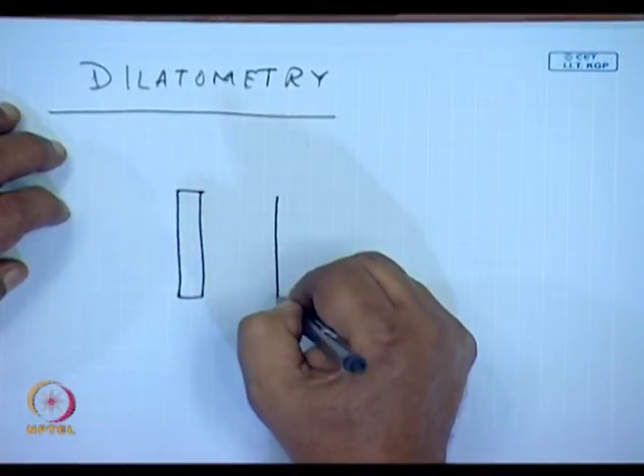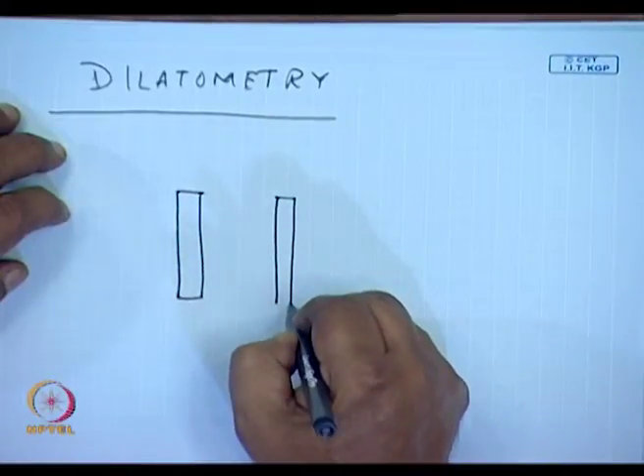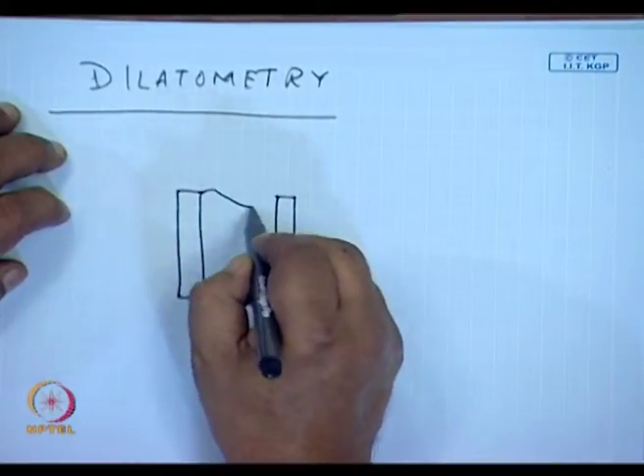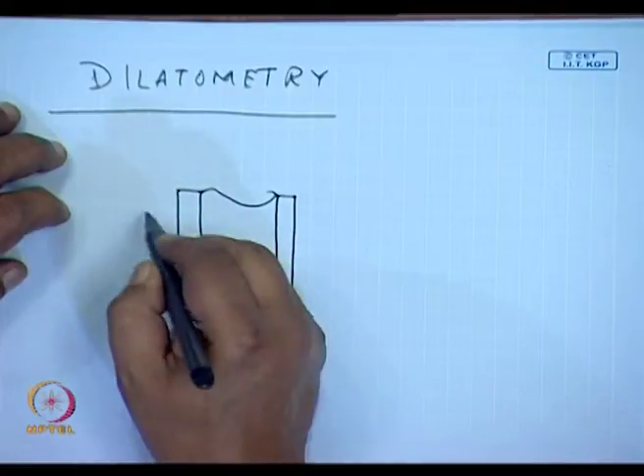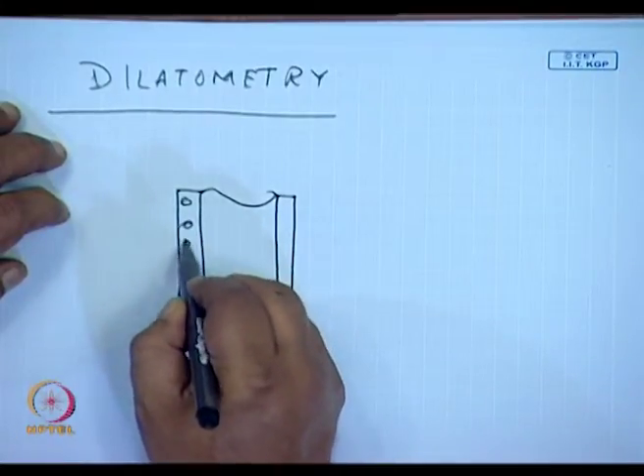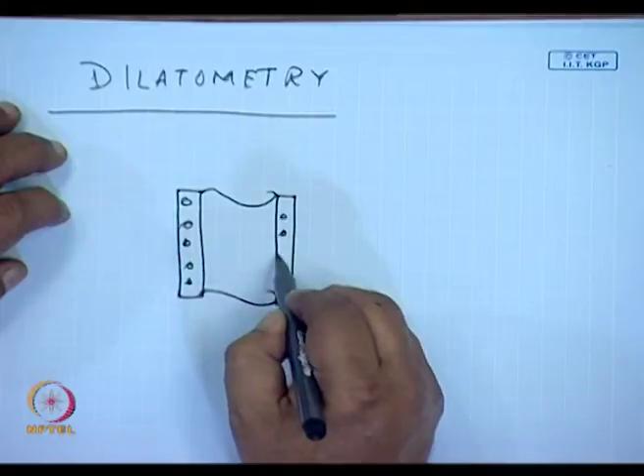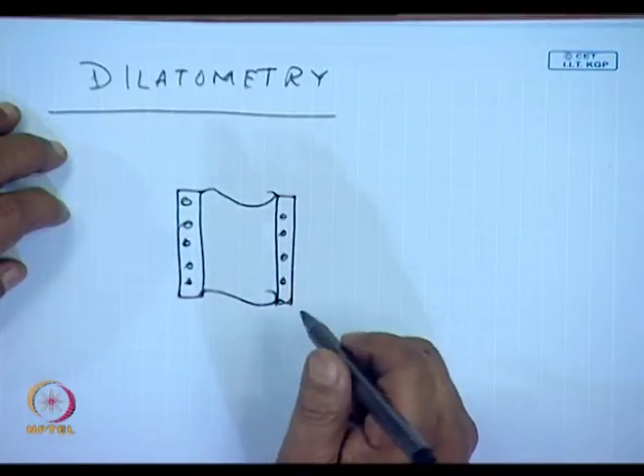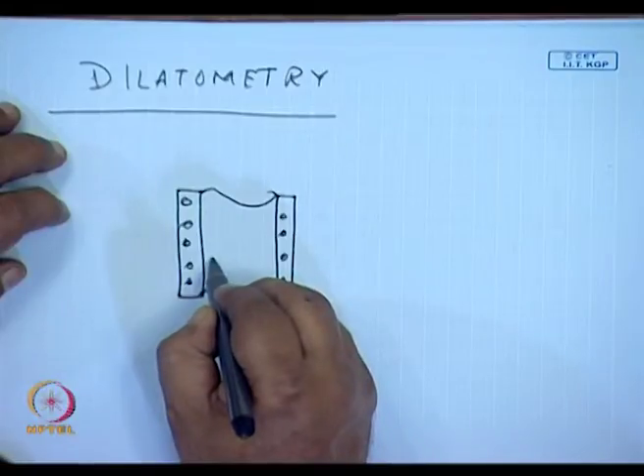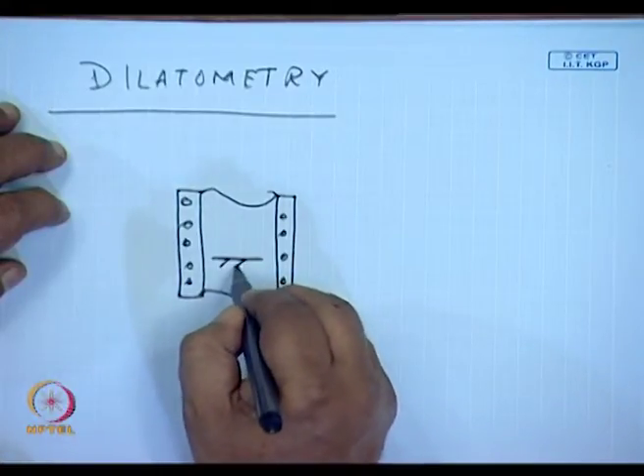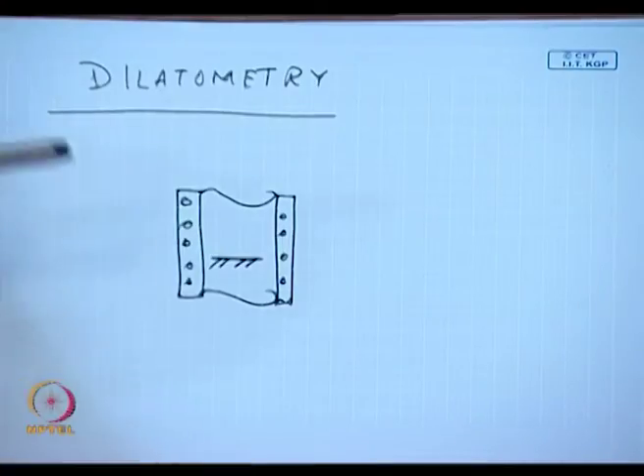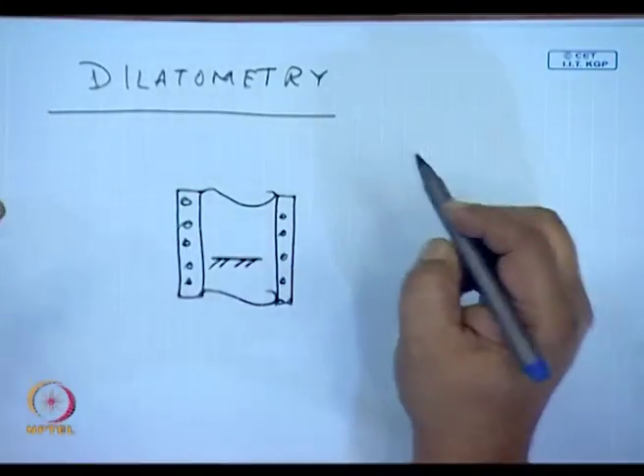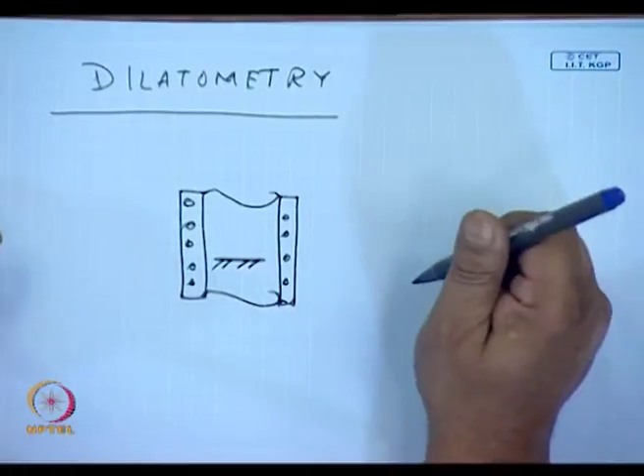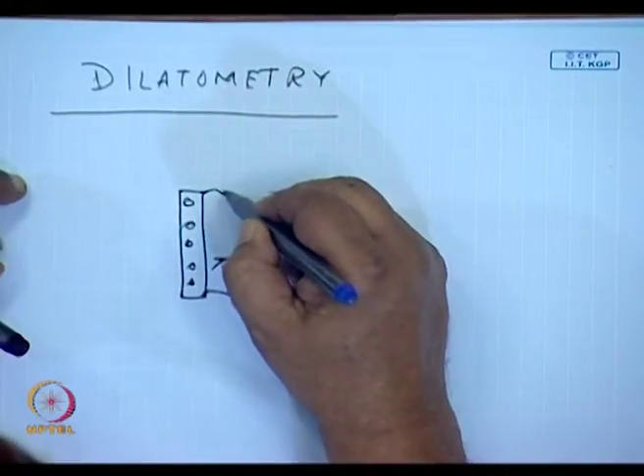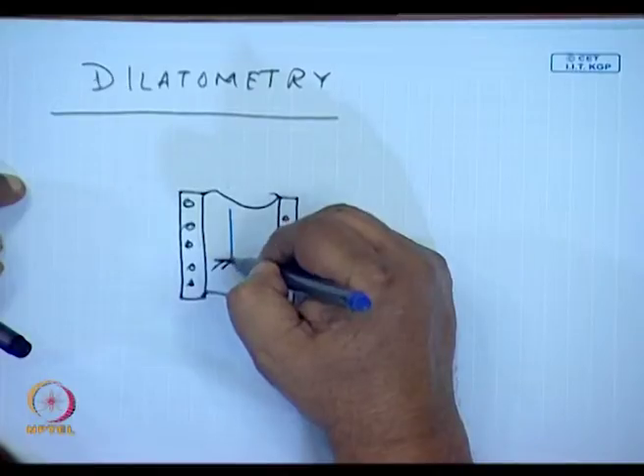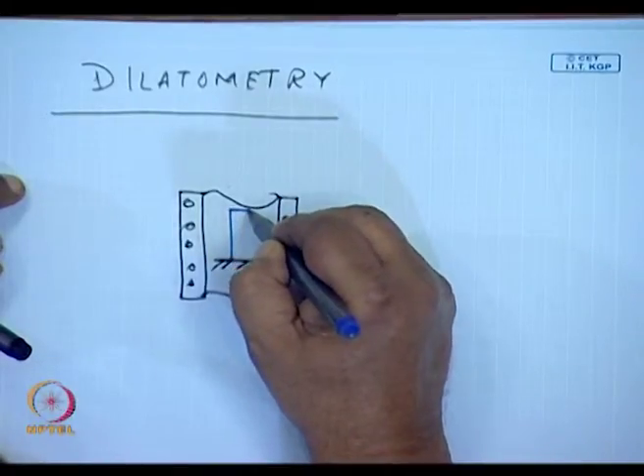This is a tubular furnace, which is heated resistively, or for very high temperature materials can be heated inductively. This is a platen which is fixed. The ceramic whose sintering is to be studied is mounted inside the furnace in a uniform temperature zone.